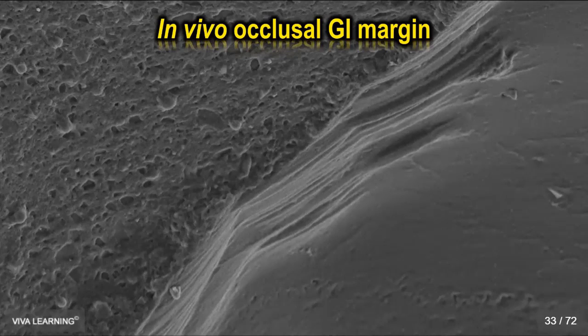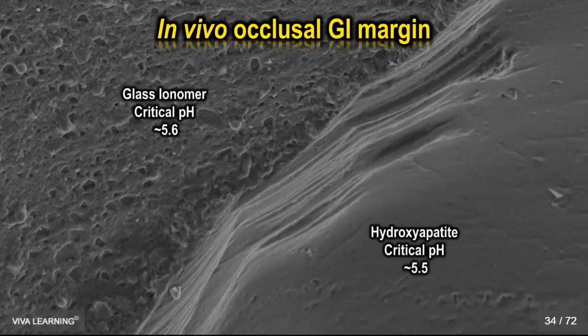But why do we see this dissolution phenomenon? That's because the critical pH of the glass ionomer is 0.1 above the critical pH for tooth structure, which means when the patient drinks something acidic, a Red Bull, a Monster Energy drink, lemonade, Gatorade, Sprite, Coke, you name it, seltzer water, pure carbonic acid, which is just seltzer water, when they're sucking on lemons, when they're eating oranges, when they're drinking orange juice, when they put an acid in their mouth, the glass ionomer has the ability to dissolve away, and it's going to do so to protect the tooth. It's a smart material like that.